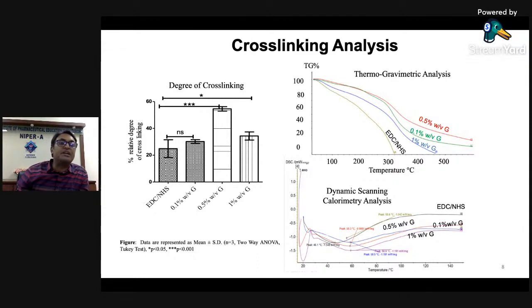We estimated the cross-linking and found that 0.5% weight by volume of graphene, when mixed with the collagen, provides the highest degree of cross-linking compared to 0.1% and 1%. One could expect 1% to show higher, but 1% graphene starts precipitating during the synthesis and was not available for the cross-linking, hence we haven't seen good material property in terms of cross-linking either.